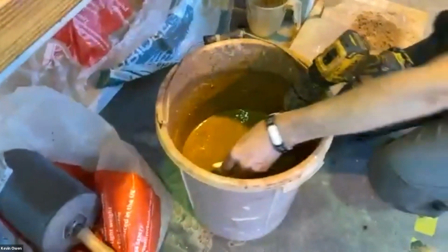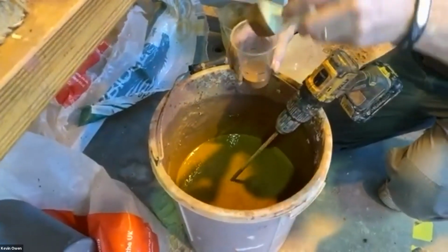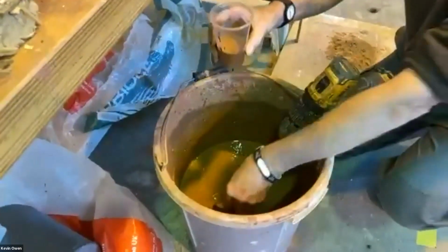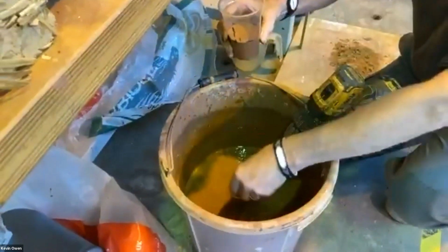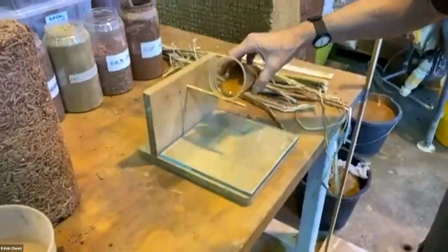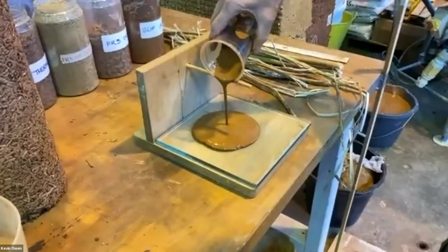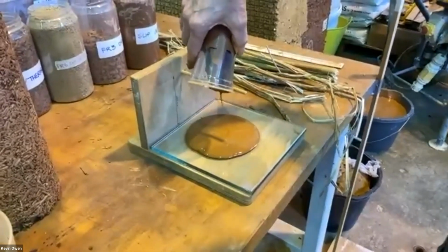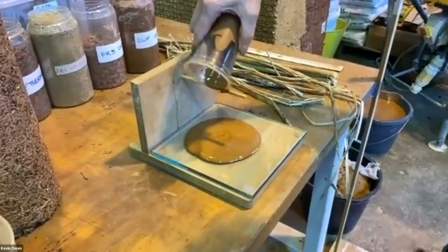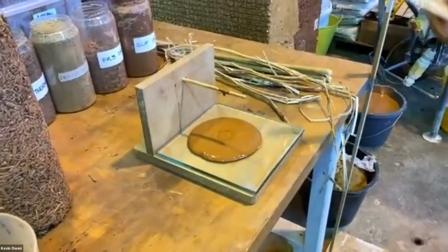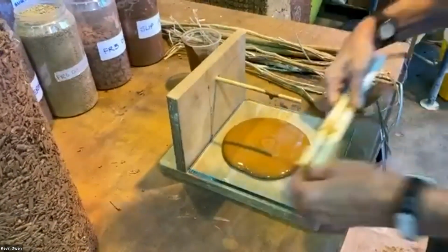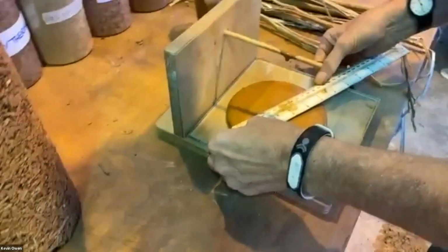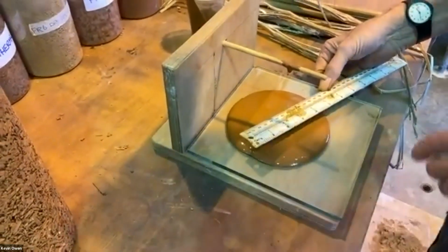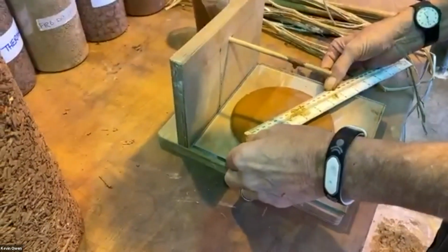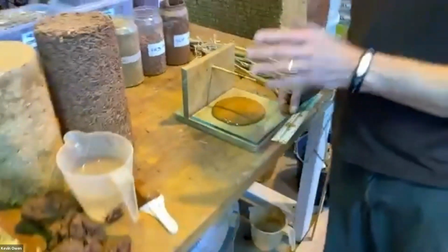Now what I do is I tip some of this into the cup, to the line that I've got. And then simply tip it over the peg. And what we found was that if we measured this, we'd be looking for a diameter of 14 centimetres. So if I lay this across there now, we're almost at 14. This material's probably dried out overnight a little bit, so I could add a little bit more water on there. But provided that was at 14, we know that it's exactly right.